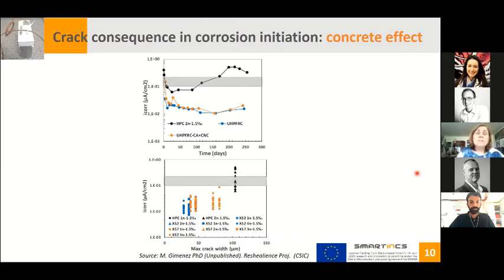But what can be the influence of the type of concrete? Here we are analyzing the high performance concrete and the ultra high performance fiber reinforced concrete, containing in this case also crystalline admixture and nanocellulose. While the high performance concrete initiates corrosion, and of course has a higher crack size, due to the type of concrete, the ultra high performance fiber reinforced concrete has not initiated corrosion, even for a crack size at the surface close to 100 micrometers.